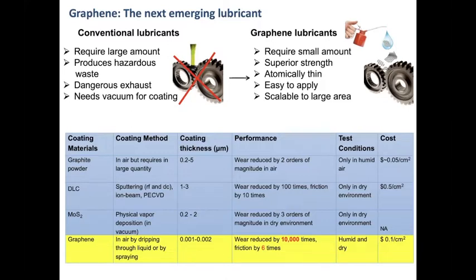Whenever you're transitioning to the humid environment, they wouldn't work. And the major problem with DLC is that you are very limited on what surfaces you can put them on, because usually it requires sputtering, like ion beam, or plasma enhanced CVD in order to deposit DLC. Similarly, MoS2 only works in dry environments. With graphene, we demonstrated that we can get a very thin coating, which can be easily applied and reapplied, and which can work interchangeably well both in dry and humid environments.